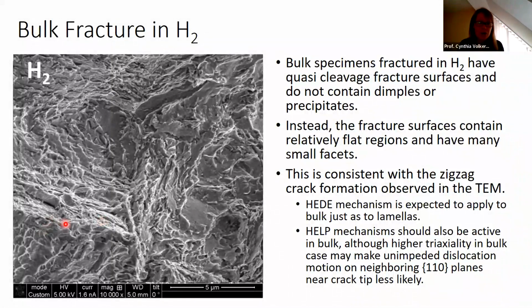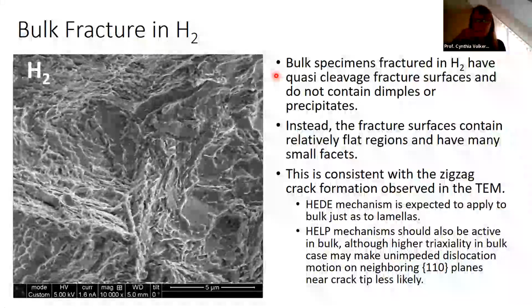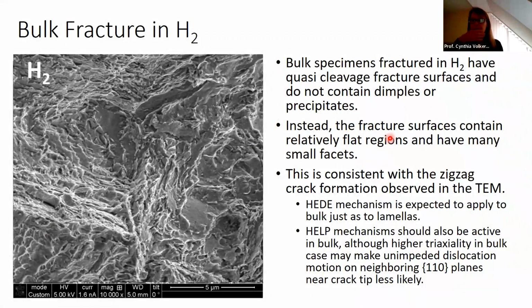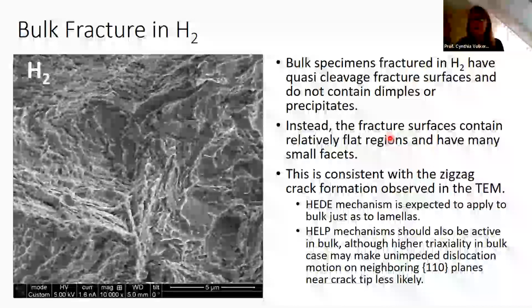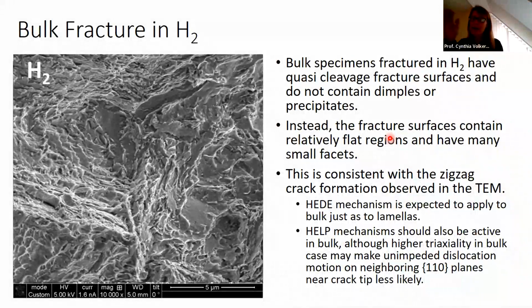I would like to now go to the question of what we learned in the lamella case for hydrogen: can we use that to explain the quasi-cleavage fracture surfaces that are observed in bulk specimens? And we believe that that's the case because our surfaces tend to be somewhat straighter and somewhat flatter. We would argue, it's a fairly phenomenological argument, that if the crack tip remains sharp, then the crack will tend to propagate where the applied stress sends it, and it's less sensitive to the microstructure, and so it will tend to be flatter to begin with.